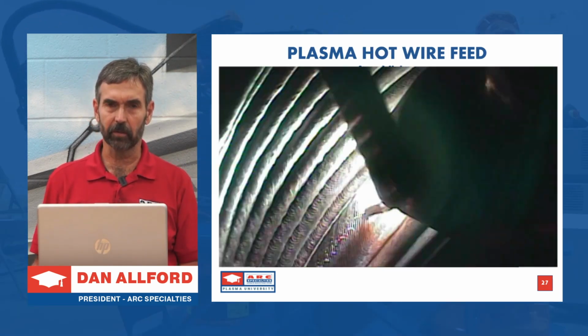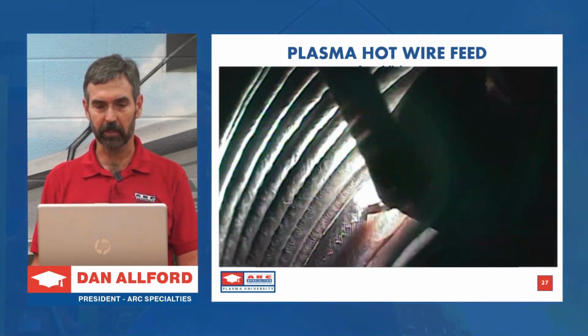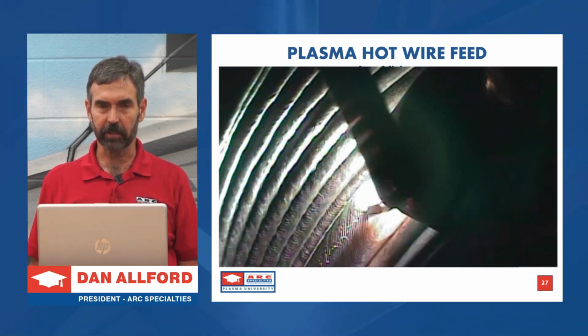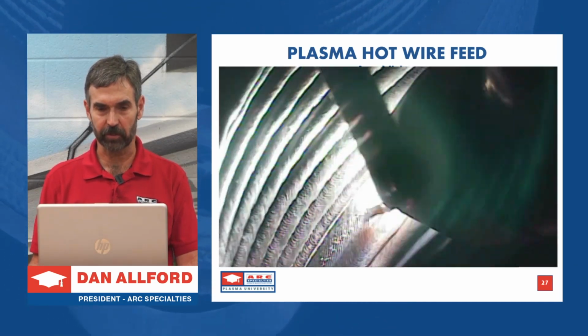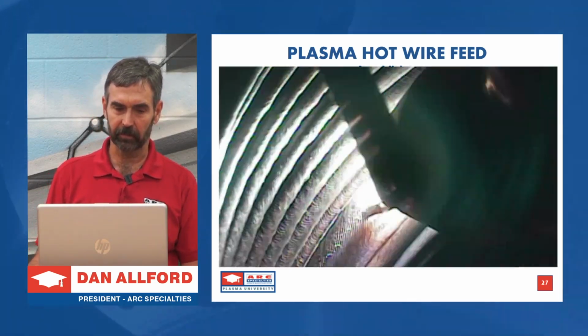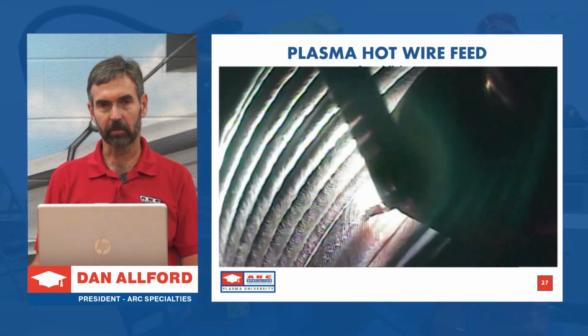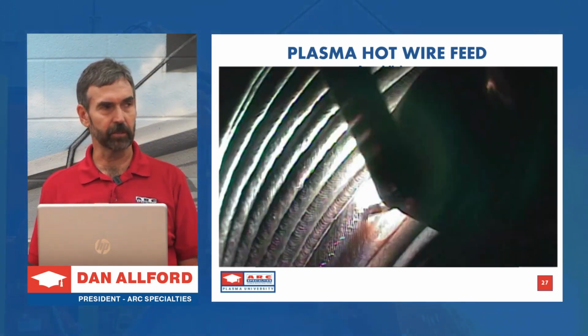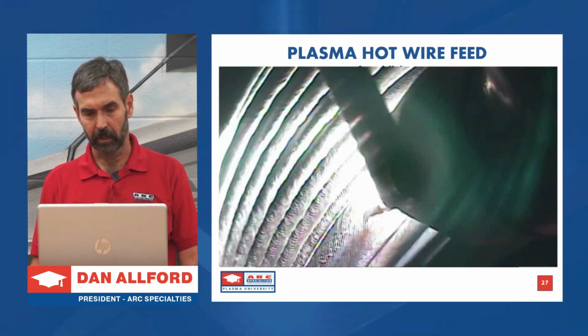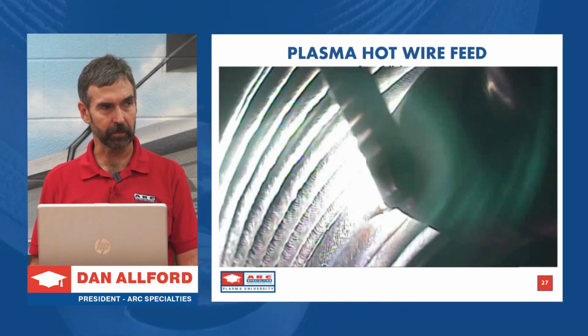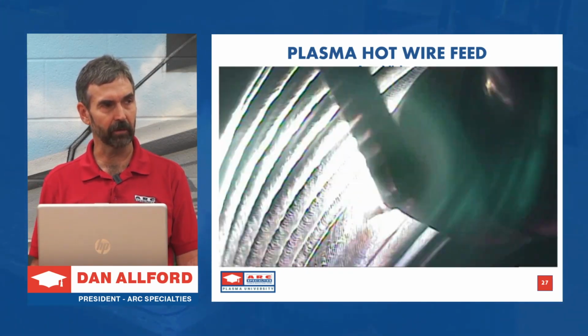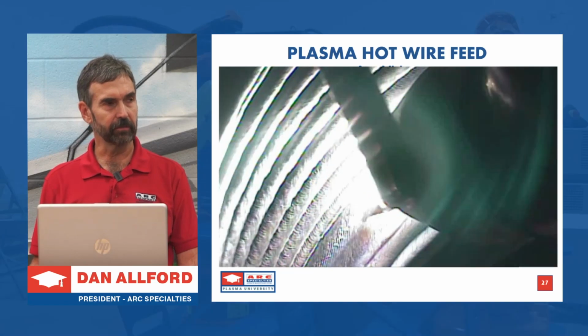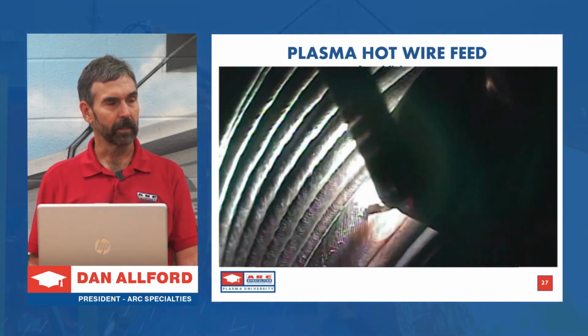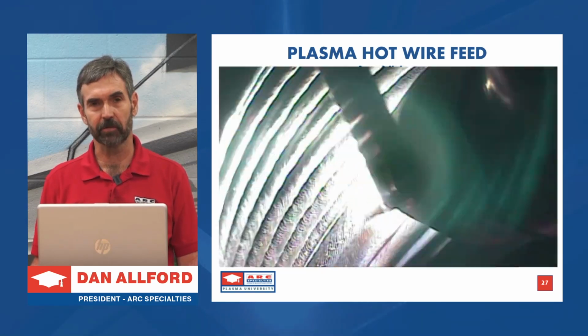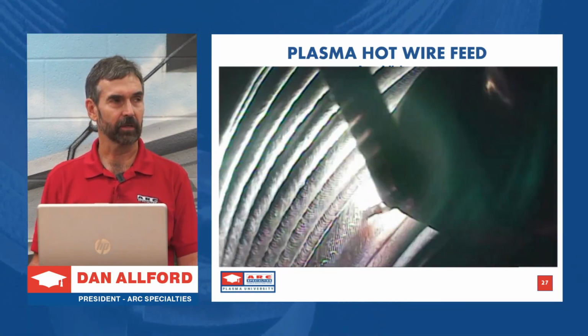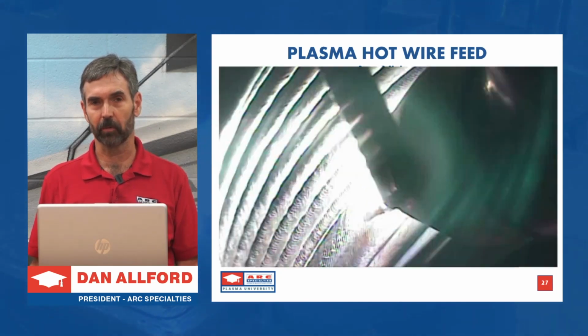So here we have an arc video of a hot wire bore torch using plasma. And what you're seeing, that pulsing, is the current pulse, so that's the waveform we're going to discuss later. You can see the wire feeding in from behind the puddle, and so you're seeing the weld come out from behind the torch. This is in the 2G position. We're welding up a wall, and the wire is preheated with a hot wire power supply, and we're capitalizing on that collimated arc that you get with a plasma. It's an interesting variation on hot wire bore cladding. It hasn't caught on yet, but I suspect that the advantages of plasma over TIG will eventually cause people to go to more and more plasma for bore cladding.